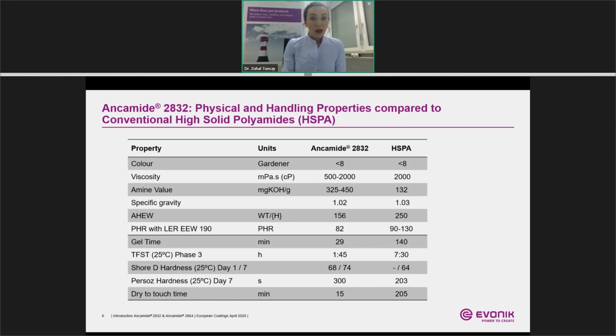Ancamide 2832 has a viscosity typically in a range of 500 to 2000 millipascal second. It has a preferred loading of 82 pHr for liquid epoxy resin, whereas the standard high solid polyamides are a little higher, in the range of 90 to 130 pHr. As expected, 2832 has a shorter gel time at room temperature compared to conventional high solid polyamides. In this case, 30 minutes, which is clearly manageable.